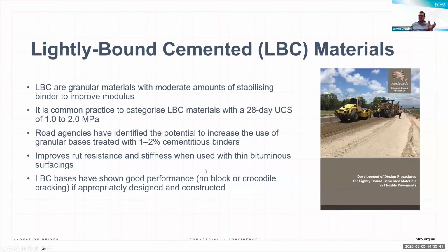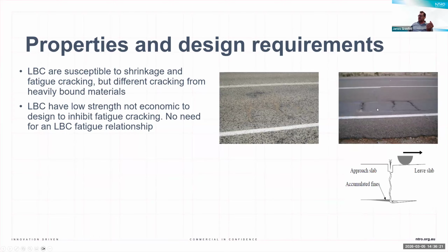So one of the things is, if we start to add more cementitious binders, it becomes stiffer and more susceptible to block cracking, which becomes a big maintenance issue. But at the very low levels of cement, it will not necessarily have a long bound life, but when it breaks down into a granular material, it's breaking down into a very fine diffuse cracking pattern, and that doesn't reflect any cracking issues up through either a sprayed seal or a thin asphalt surfacing that's laid over the top of it. So what we're trying to engineer against is this type of issue where we end up with block cracking.